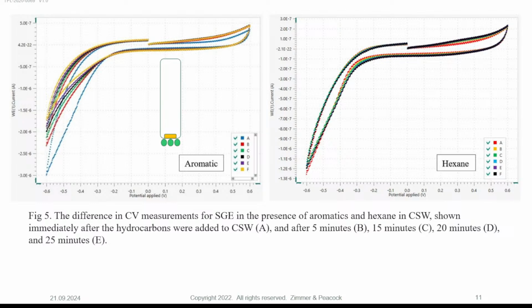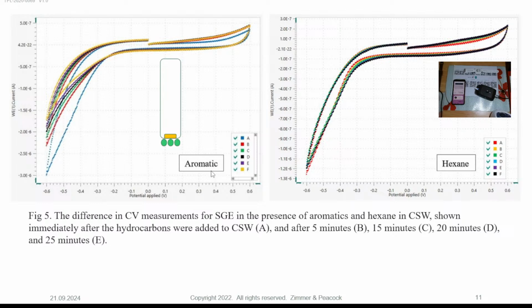When you do a similar thing in hexane, you do not get that. So it tells me that hexane is not depositing onto and blocking your electrode. I was thinking it might be electropolymerization that's happening with the aromatic compound, but I don't really see much evidence of electropolymerization, so I'm not going to say that it is electropolymerization going on here. But you can see a difference between the hexane and the aromatic compound. The hexane stays consistent whether you've been soaking for 5 minutes, 15 minutes, 20 minutes, or 25 minutes; it all stays the same. So hexane is not absorbing and blocking your surface in the same way. So that's your simple gold electrode.